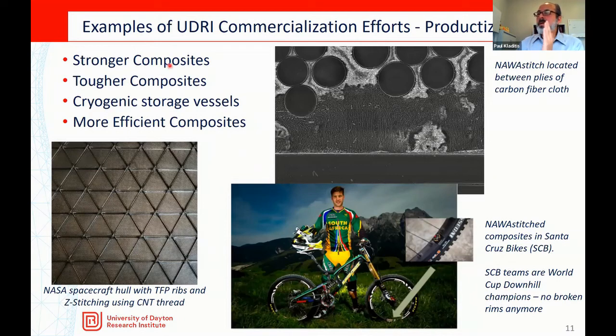So we use the carbon nanotube based technologies to make stronger composites. And here's an example of the vertically aligned CNTs placed in between 2 plies of carbon fiber. There's a nice close-up shot. These are the carbon fibers coming out at you, probably less than 10 micron diameter fibers. But this increases many mechanical properties of the composite by putting the vertically aligned CNTs in there, or it's called NAWA stitch. Here's an example of making a spacecraft hull where the ribs are stitched down using TFP and the CNT thread stitching.